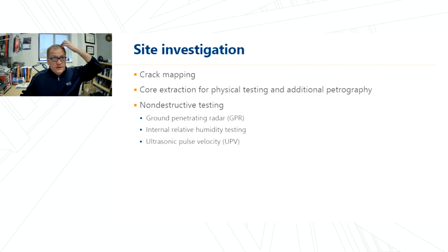So we proceeded to do a site investigation as part of our process, which included mapping of the cracks, extraction of additional cores for physical testing and additional petrography. We also did some non-destructive testing: ground penetrating radar, internal relative humidity testing, and ultrasonic pulse velocity testing.